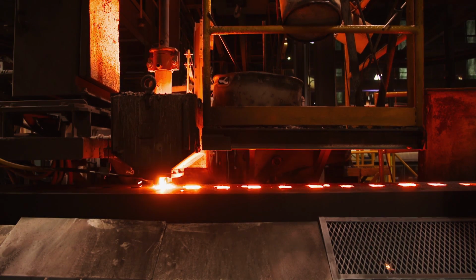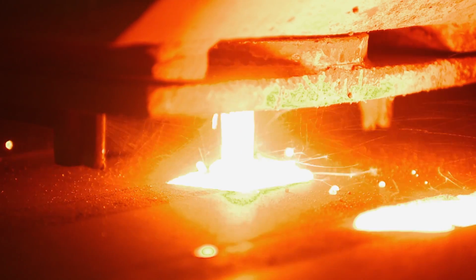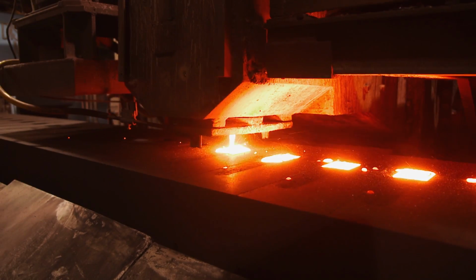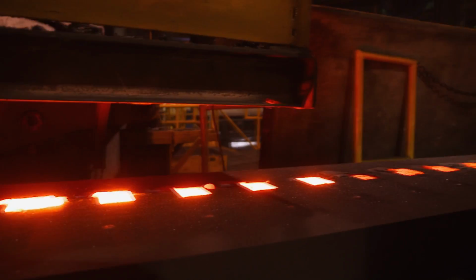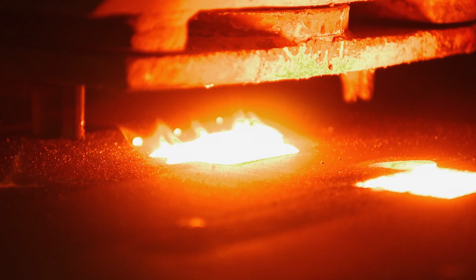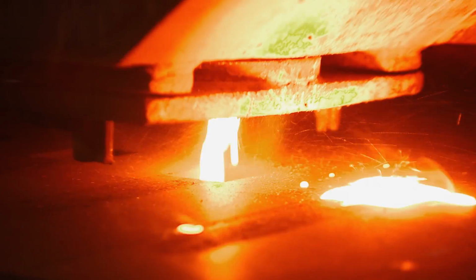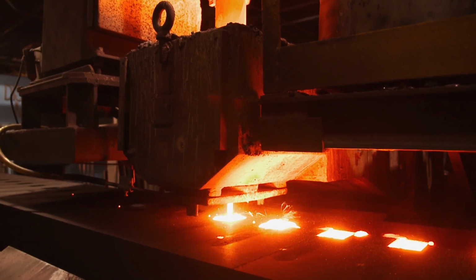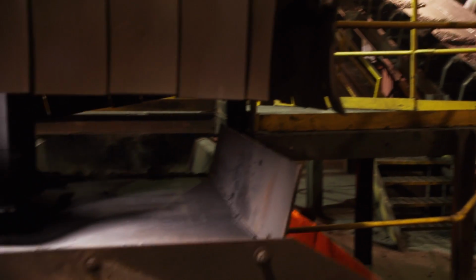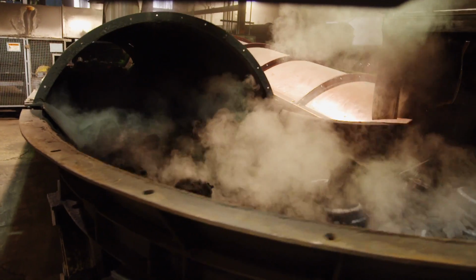The iron is automatically poured into the molds as they index out of the machine. The molten mix must be poured between 2,480 and 2,520 degrees Fahrenheit. The reason for that is if we pour too cold, the metal will freeze before it nets together. If we pour too hot, the metal will burn into the sand. Next, the freshly formed cookware is broken free of its sandy mold and put through a shot blasting machine.